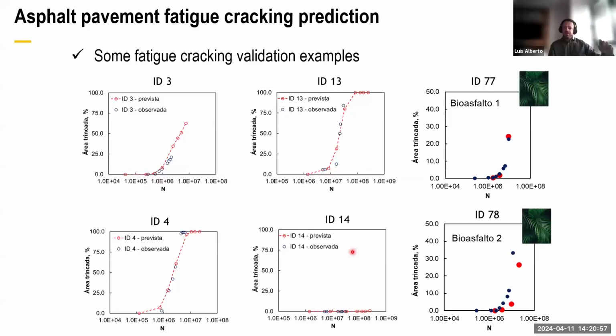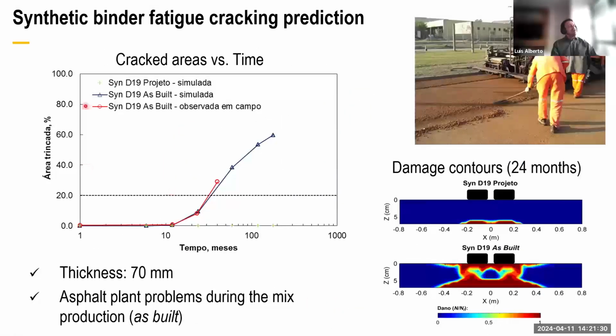In São Paulo, we have some special soils with lateritic behavior. So the engineers from this region can combine aggregates with this soil to produce really good unbound materials, stabilized materials. And since they produce a very nice pavement structure by using these materials, the pavements present very nice performance. And whenever we consider these properties in the analysis, we got very nice performance here. So that's good. This is another example. It's a very different material here. It's a synthetic binder.